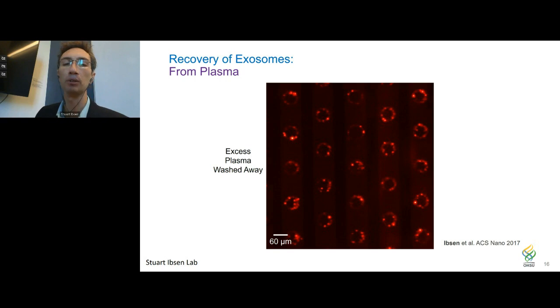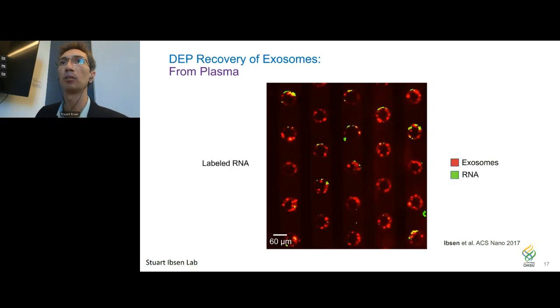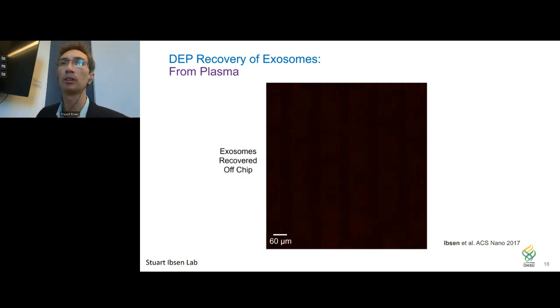And so we were able to do that here with a stain for RNA. So about a third of the particles that were collected had stainable RNA content. And we were able to recover these particles off the chip and then analyze the RNA, and we could find cancer-related mutations that we knew were in the glioblastoma cell line. So this is really exciting to be able to see actual cancer mutations in the RNA that's been collected by this dielectrophoresis technique. And then you can see that we can recover most of that material off the surface of the chip.